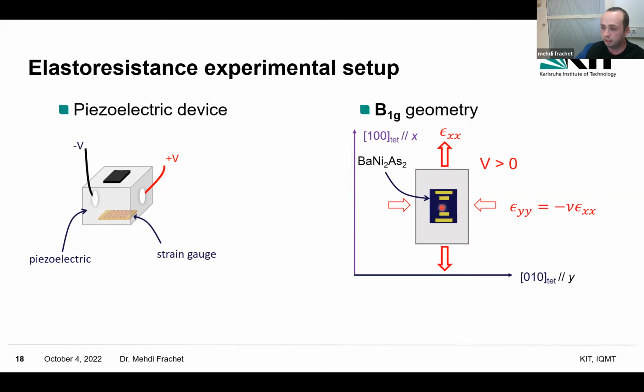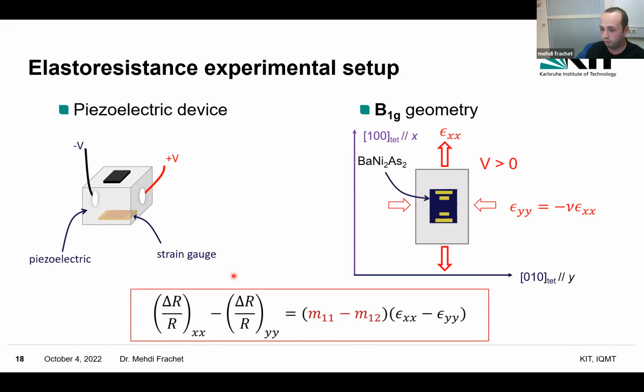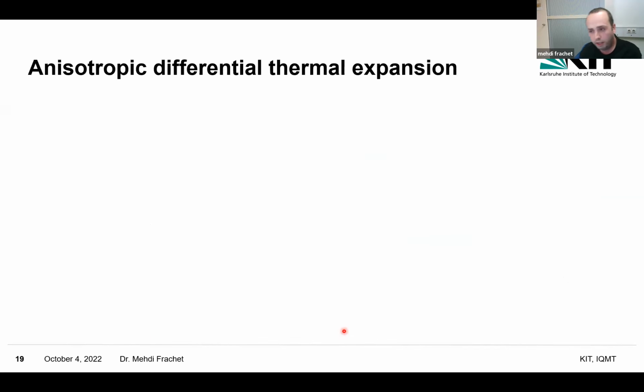And we can measure electrical resistance both along the pulling direction, but also perpendicular to it. And what I wanted to show you with these gold rectangles is the orientation of the electrical contacts. Okay. So we measure the resistance anisotropy, we measure the strain, and so we can extract this m11 minus m12 elastoresistance coefficient that again belongs to this B1g geometry in the tetragonal phase. One thing I would like to mention, and that's important for the following, is that the thermal expansion of the piezoelectric device is actually anisotropic.